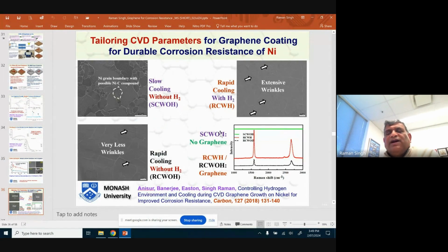But as I said, our interest shifted mainly to nickel because we had interest in developing multi-layer graphene, and it is nickel which can develop multi-layer graphene far more easily. We started to work on tailoring the CVD parameters further so that we can develop graphene of good quality, graphene with fewer wrinkles. And in one particular condition, where we did rapid cooling after CVD at 1,000 degrees Celsius, but in an environment without hydrogen, it produced graphene with fewer wrinkles, and Raman spectroscopy proved the quality of the graphene.